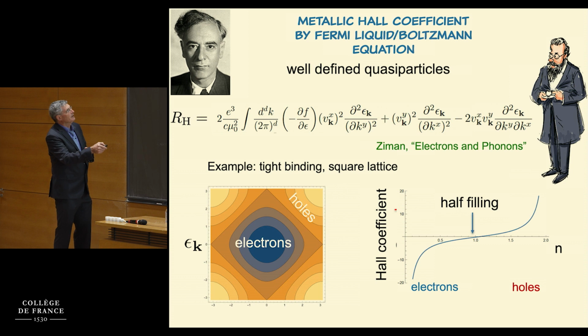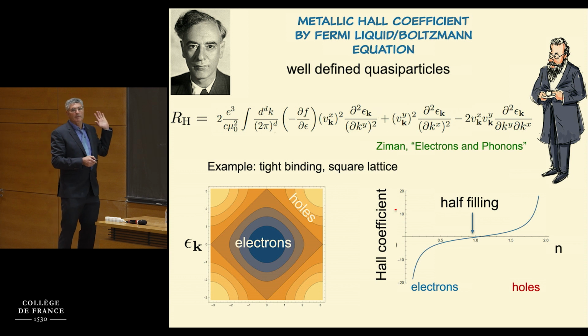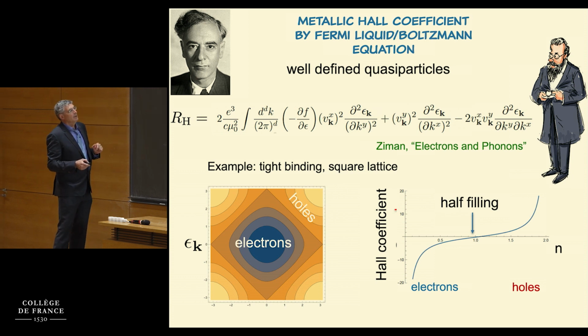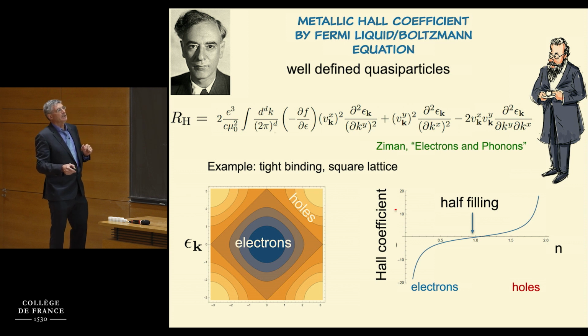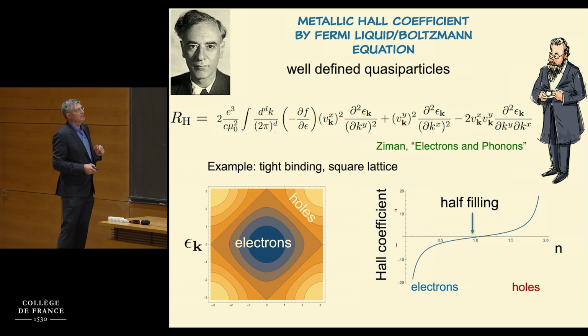And if you fill above half filling, it should be positive, and therefore the Hall coefficient with this formula crosses 0. No singularities anywhere in the band. There is a singularity at the bottom of the band and the top of the band, at n equals 2 and n equals 0, but nothing in the middle. And that's a general property: you can add next nearest neighbor interactions, you can add many, many things to this theory, but the singularities are really determined by the empty or the full band.